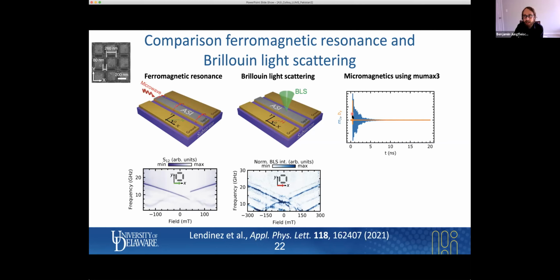We apply it along the y direction, and then we record the average magnetization and the average magnetization components and the spatial distribution for a duration of 20 nanoseconds, as you can see here. I'm plotting here the Mz direction, so the magnetization in the Z direction. We can now zoom in and see that once we hit the system with a sinc pulse, the oscillation starts. So this is shown in blue. And if we wait long enough, the sinc pulse has decayed and we see steady oscillations. So this is done for one particular field.